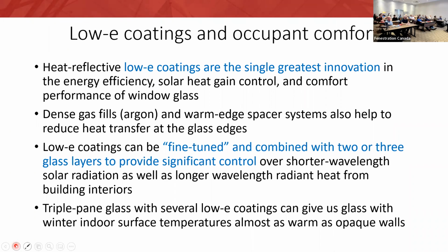And the difference between high solar and low solar coatings is that both of them are doing about the same job in keeping the heat in. U-factors don't vary very much, but the high solar gain coatings are admitting more of the solar energy spectrum, the sun's heat, and the low solar gain coatings have a denser particle density, and they're trying to capture mainly visible light. They're capturing less of that solar heat energy, but still doing a lot, still being just as effective at keeping the indoor heat in.